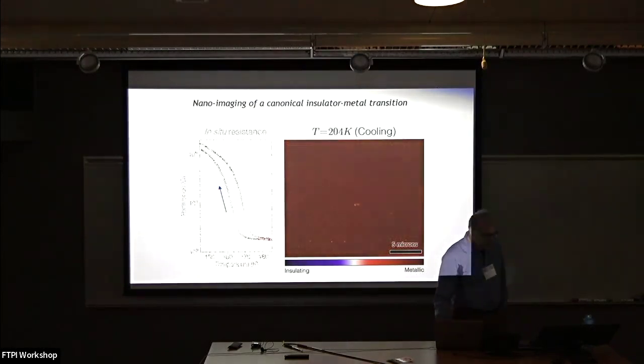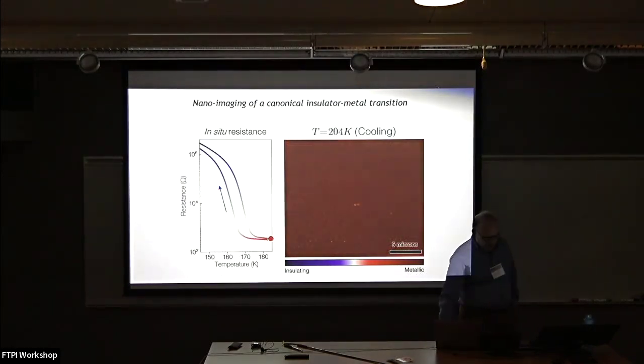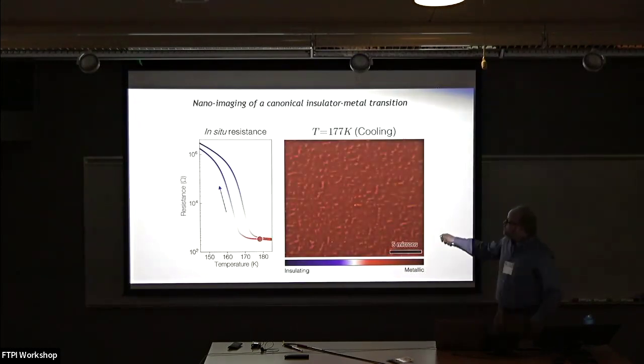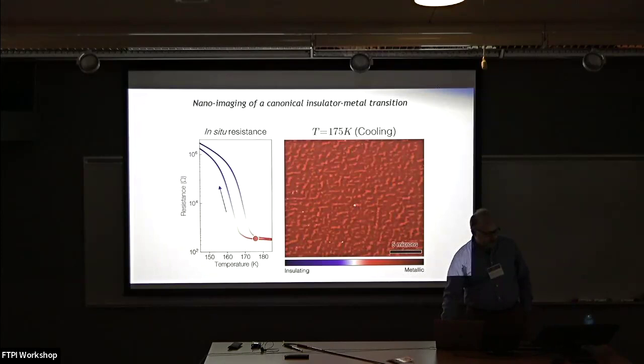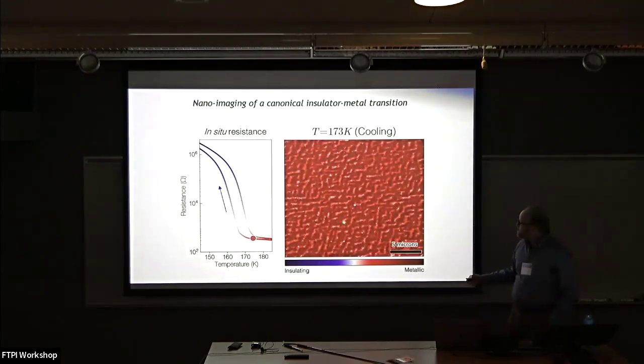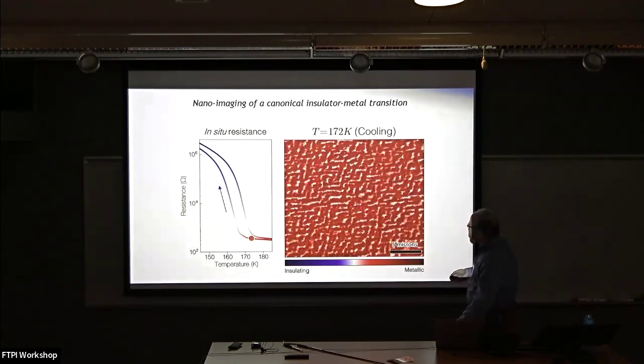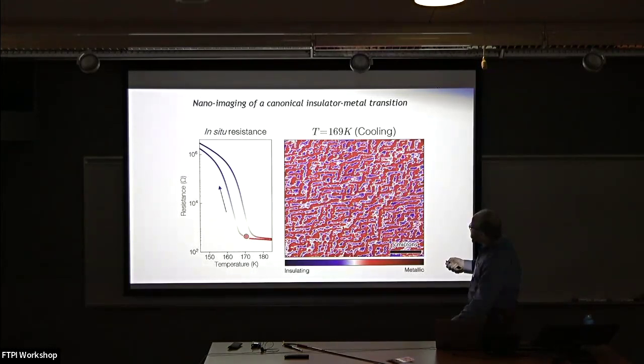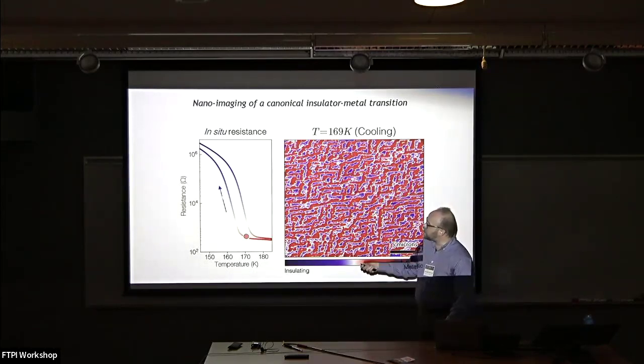You should be right to be suspicious when you see values somewhere in between the two of these. But let's just go ahead and see what happens as we cool this fellow down. So again, we're scanning some sort of optical probe over the surface of this material, 20 by 20 micron square. Same field of view all the time. And as we cool, the first thing that you'll begin to notice is that we nucleate some other phase. It's not metal. It has a lower conductivity. One should rightly ask, what is its conductivity? Clearly, that conductivity gets more blue on the scale as we go lower and deeper in temperature, as you can also follow the bouncing ball here on the resistive transition. You can see we're going into the insulating state.